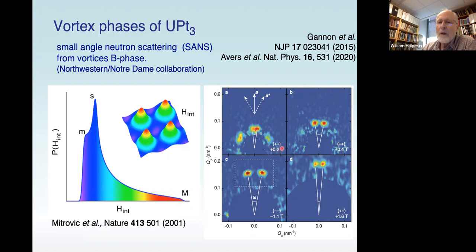However, this is at low field. This field is approximately the same field that Huxley did small angle neutron scattering with. But if you carry to larger magnetic fields than what Huxley had performed, you can see that this spot up here starts to split apart. This is at 0.4 Tesla, now up to 1 Tesla. You see it splits apart more. And then at even higher field, it seems to decrease in its splitting.